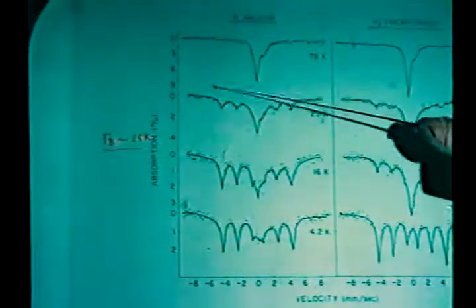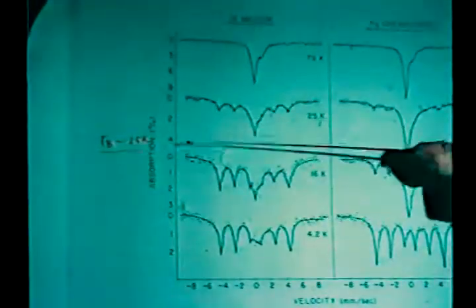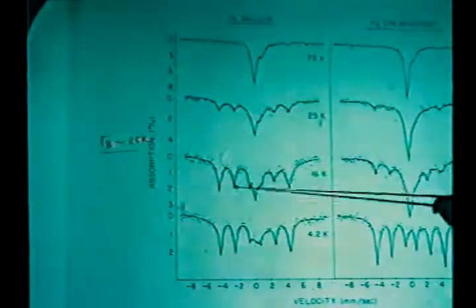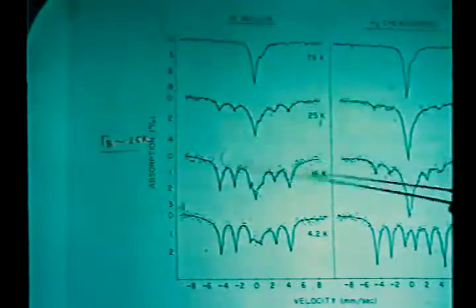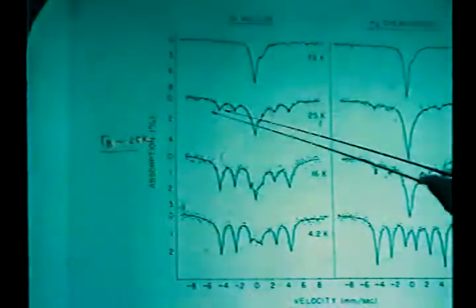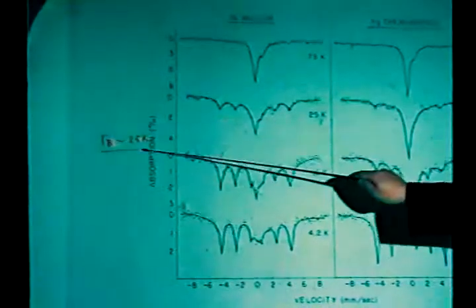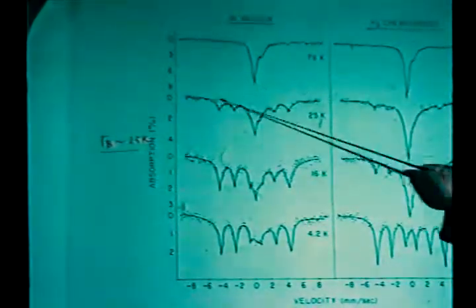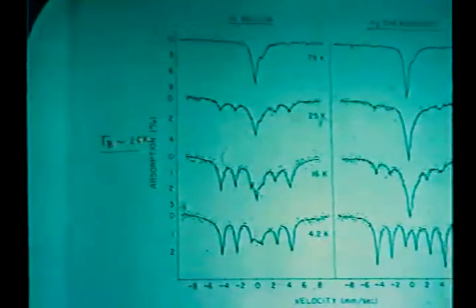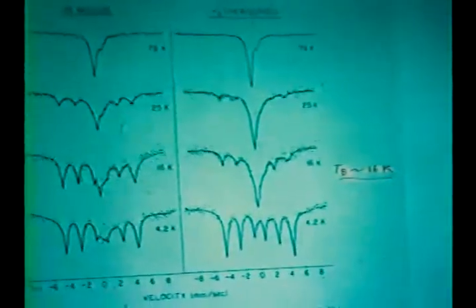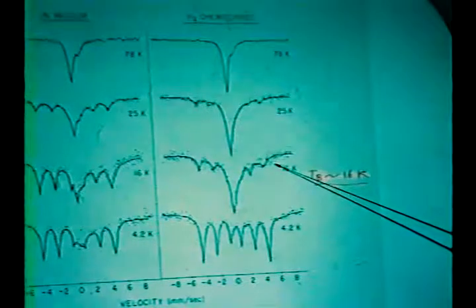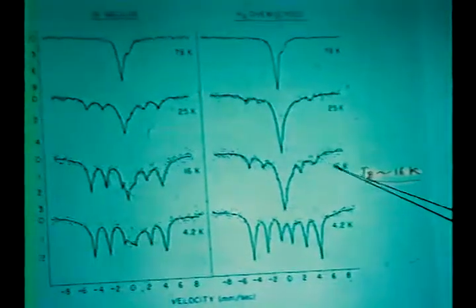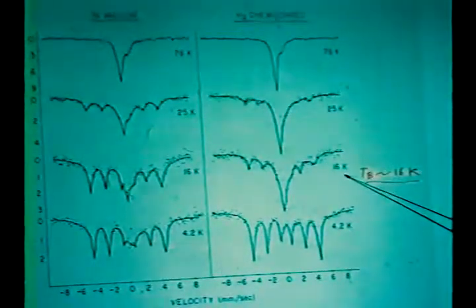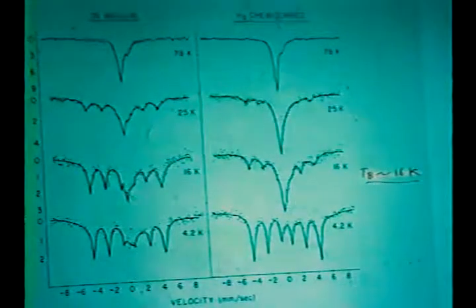If we lower the temperature, passing the blocking temperature, we will see a 6-line pattern, and that is the magnetic spectrum. From this spectrum, you can see the blocking temperature is about 25 K. But if the surface is adsorbed with hydrogen, the blocking temperature drops to about 16 K.